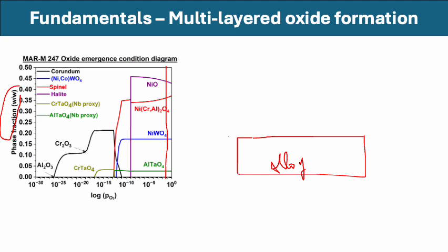Because this is purely thermodynamic and only chemical thermodynamics is being accounted, though, because free energy has three components. One is the chemical free energy, which is just due to the phase transformation, and there are two other free energies that are important in considering different phase transformations, that is interfacial free energy and the strain energy. That is not considered within this diagram, but let's for a moment assume that we care only about the